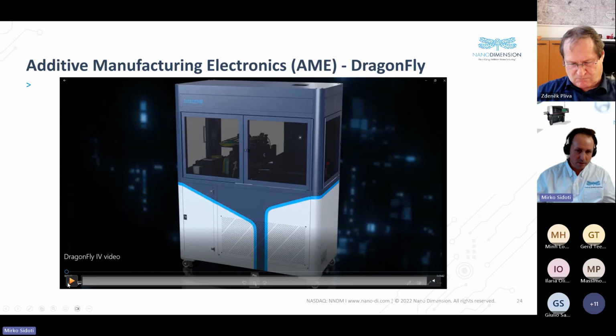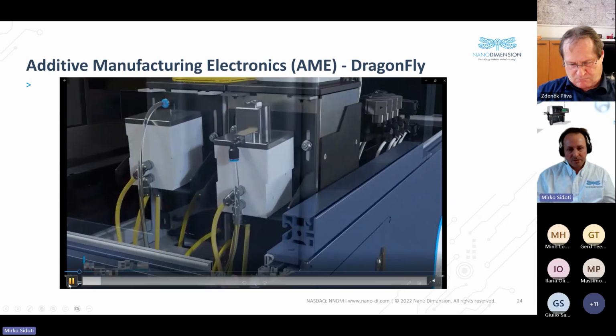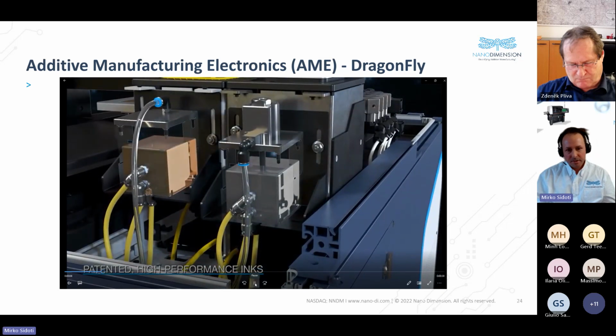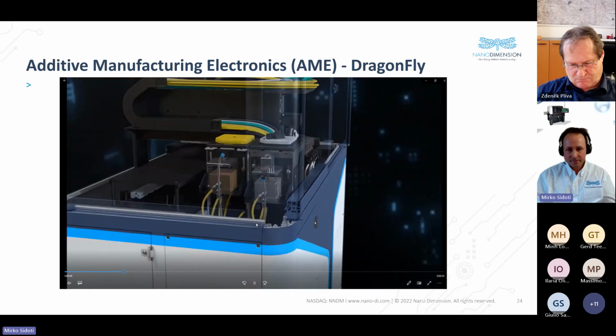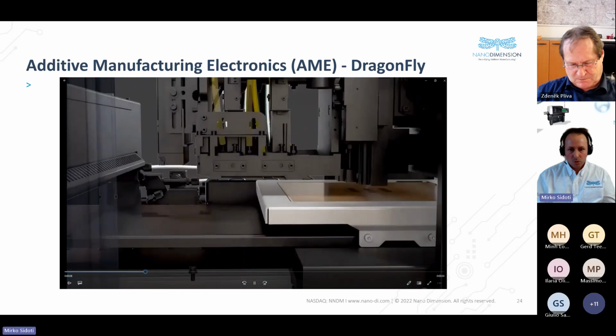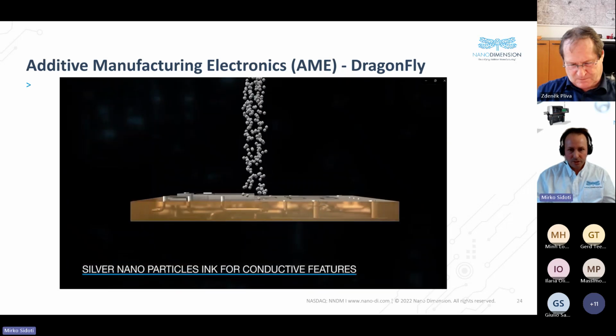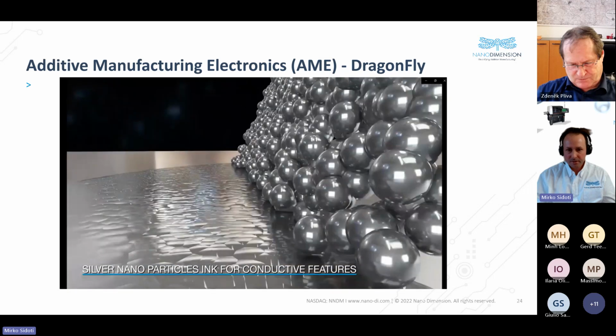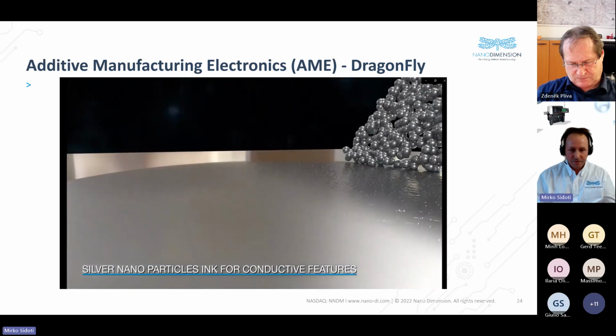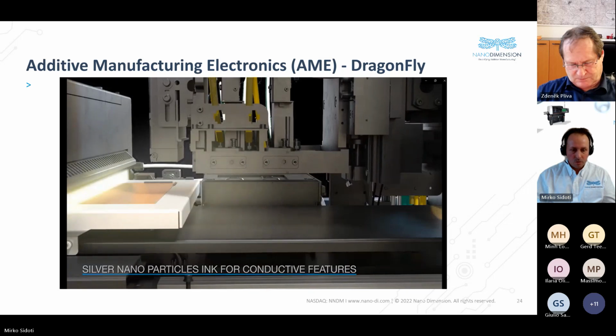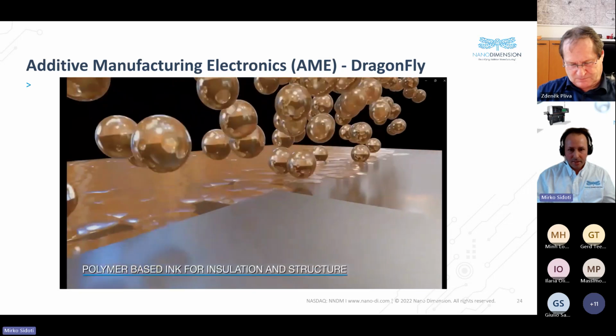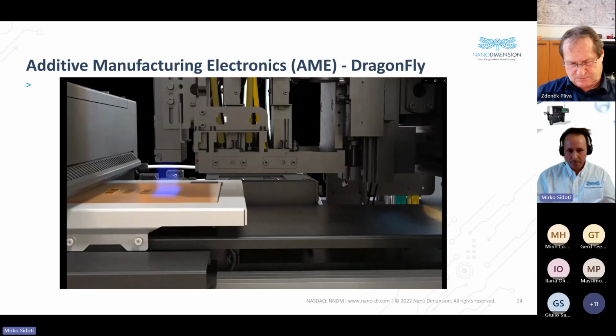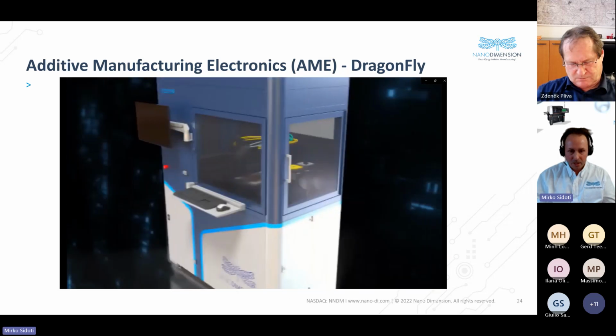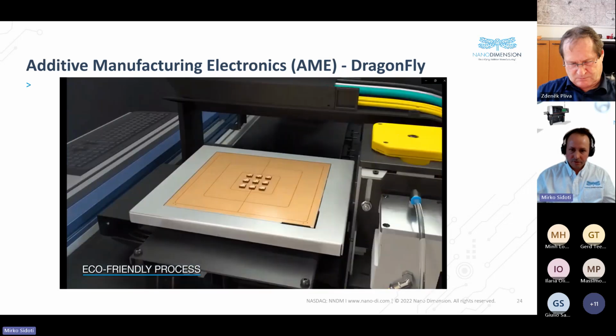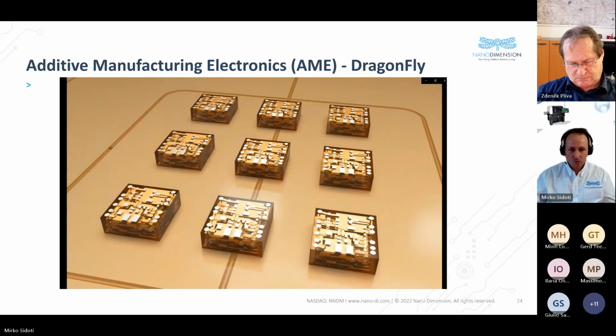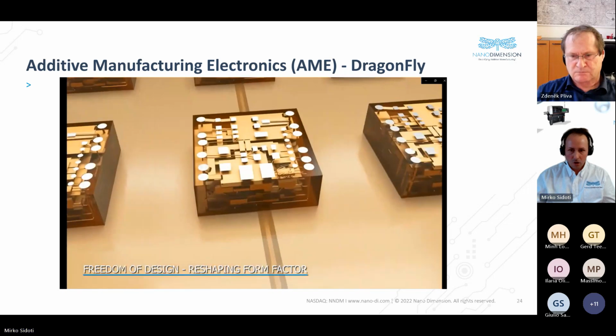What we are printing, as I said, this is the process. I show you quickly. So the two tanks with the two inks that are delivered to the print heads. The two materials are jetted. As I said, we are jetting droplets of 36 micron diameter. We jet the conductive ink, we sinter, and then we jet the dielectric ink and we cure using the UV. We do that layer by layer, and we grow up the structure in a fully additive way to achieve the final 3D object.